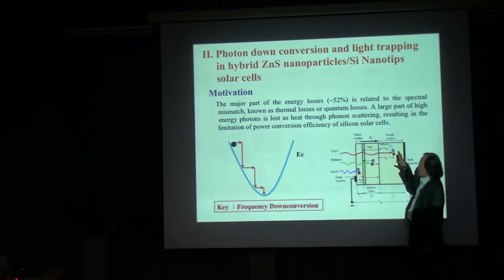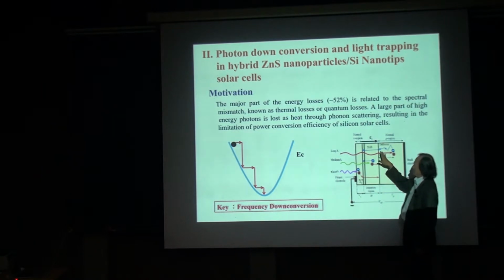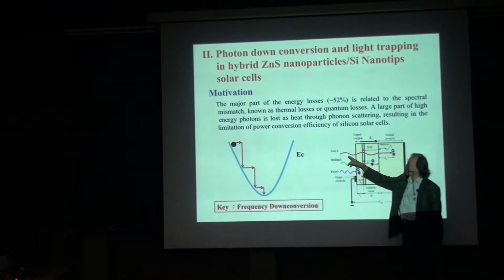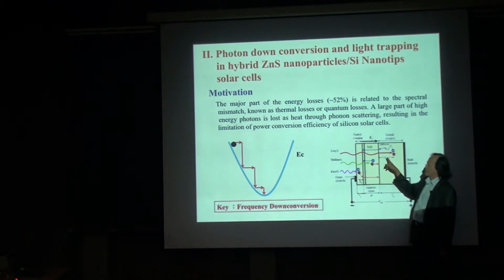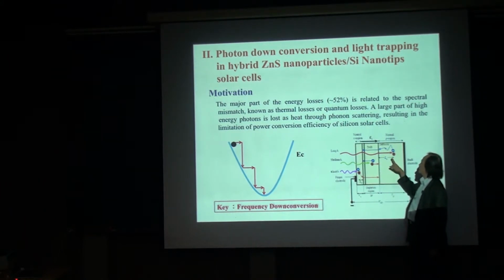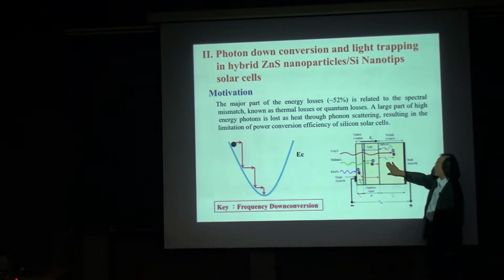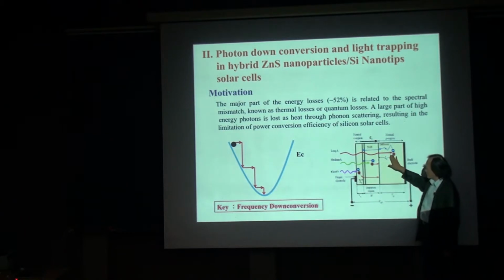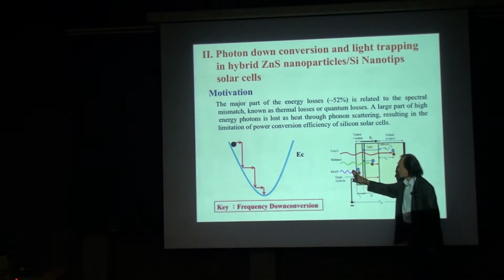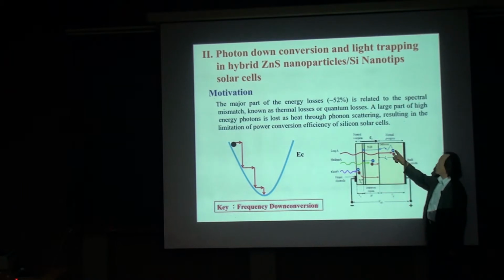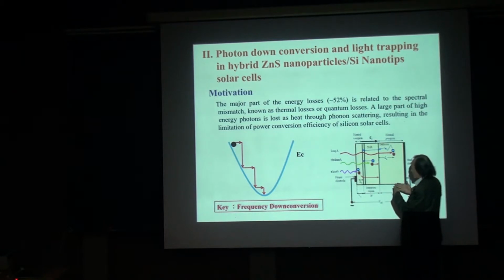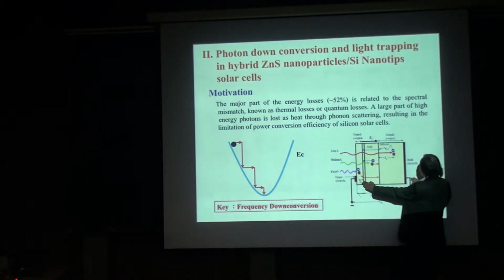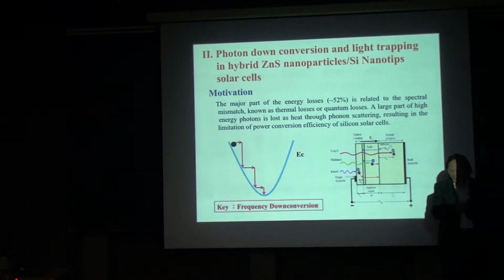However, if you have incident light with a longer wavelength and the penetration depth is deeper, you can excite the electron-hole pairs inside the bulk region. The bulk region has much fewer defects than the surface. So the electron-hole pair in this region, after generation, has a much larger possibility to travel to the electrode and contribute to the solar cell efficiency.